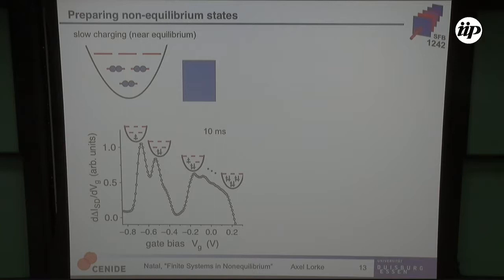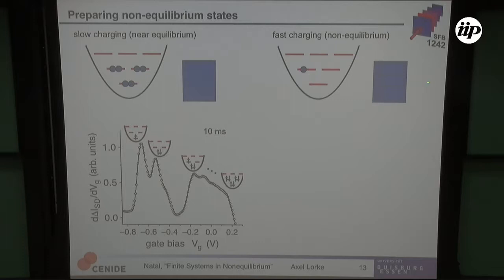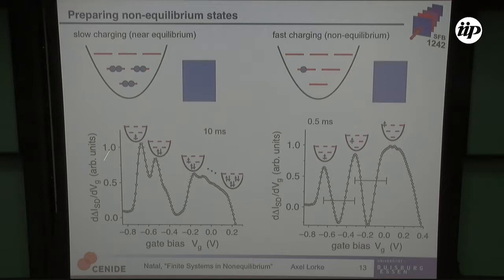But if you are bringing the Fermi energy up very quickly, you are able, because tunneling into the higher states is exponentially faster because of the barrier being lower for the higher states, you are able to tunnel into the excited states before you fill the lower states. And if you do this and look at the same spectrum, you see now the density of states of the empty dot ensemble. And here you see again the harmonic oscillator, because you see three equidistant peaks. This is the S shell, this is the P shell, and this is the D shell.